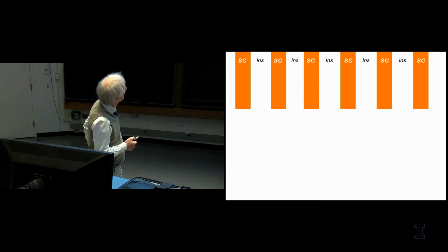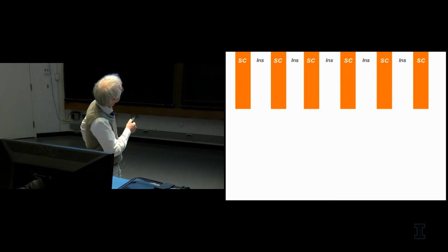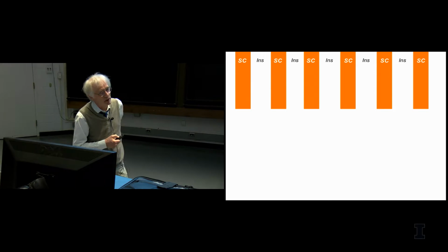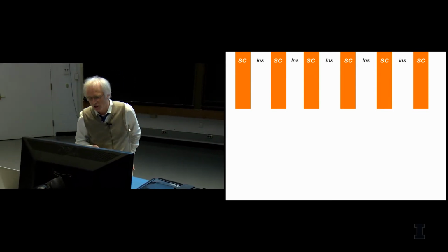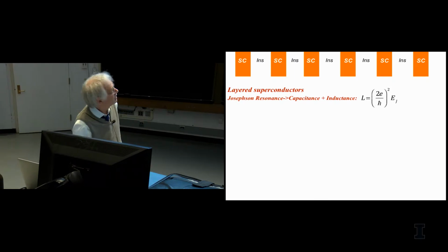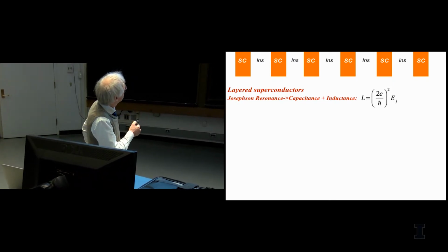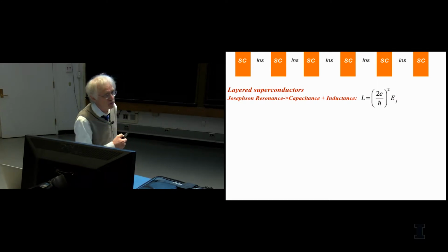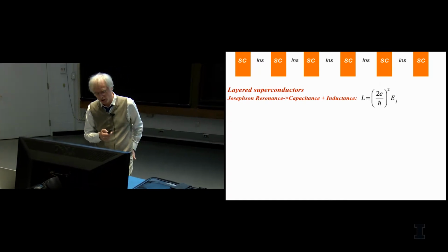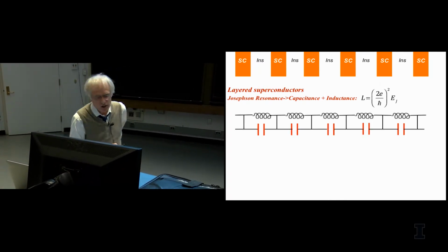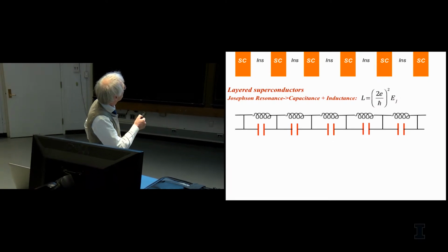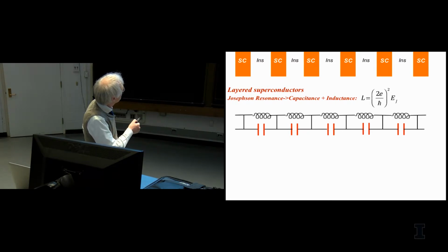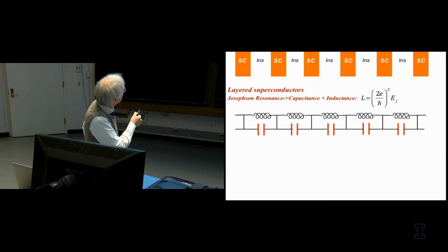Cuprates can be thought of, if this is the c-axis, as stacks of superconducting layers. These are copper oxide and oxygen planes separated by insulating barriers. Indeed the material is like this, so you can think of it as layered superconductors where you actually have the Josephson coupling between those planes. These planes form sort of a capacitive stack of many capacitive plates on top of each other, and between each of those planes the connection contains a capacitive link, which are the plates themselves, but also a Josephson coupling, which is the tunneling between one layer and the next.